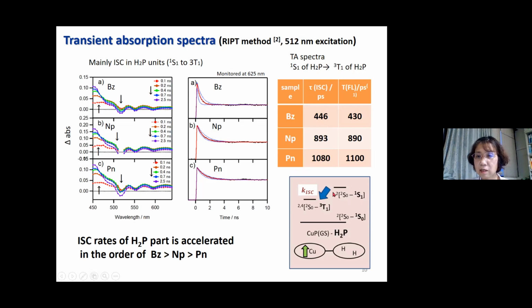And actually, the intersystem crossing rate can also be determined by fluorescence spectroscopy, and these values show very good correspondence, so we can believe that this expresses the intersystem crossing rate of the three dimers within the free base. Actually, the free base monomer only has intersystem crossing of about 12 nanoseconds, so in the dimer, intersystem crossing is much accelerated, and this order is similar: phenylene, naphthalene, phenanthroline, as in the energy transfer from the copper to the free base.